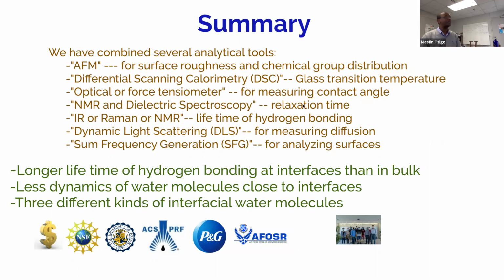We have also measured the contact angle, which in experiments uses an optical or force tensiometer. We have measured the relaxation time. In experiments, you will need NMR or dielectric spectroscopy. We have also measured the lifetime of hydrogen bonding, which is similar to using IR or Raman or NMR. For measuring diffusion, you need dynamic light scattering. We have analyzed the surface properties.